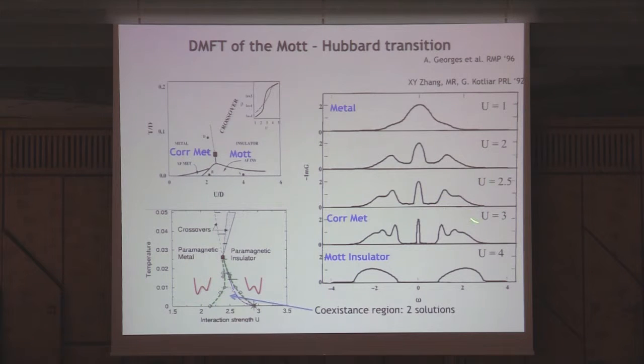If you keep on going, you'll find an intermediate value of u, a critical value of u, where this quasi-particle peak becomes very, very narrow, and all the weight is already in the Hubbard bands, and beyond that, you open a gap, and you have your Mott insulator.